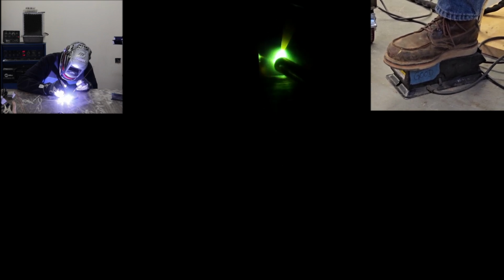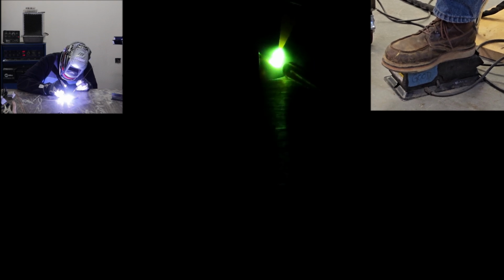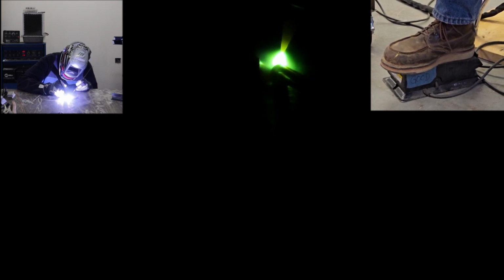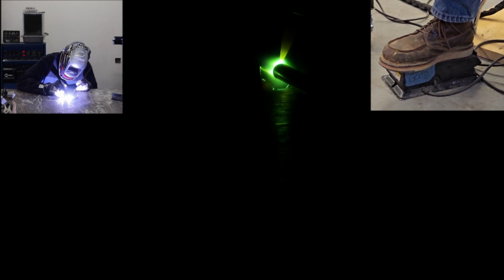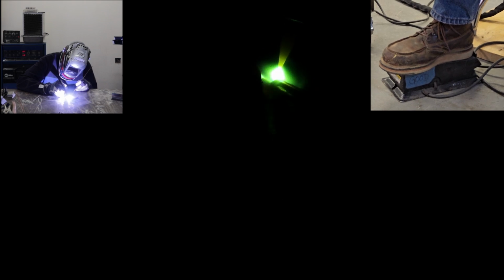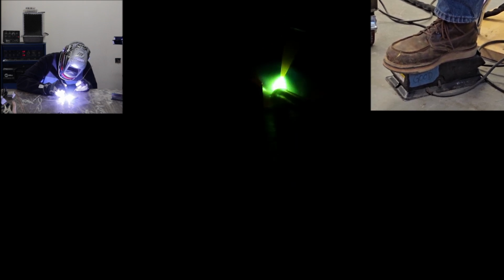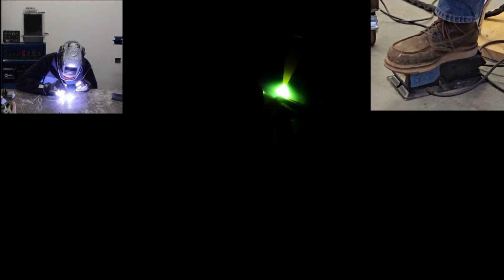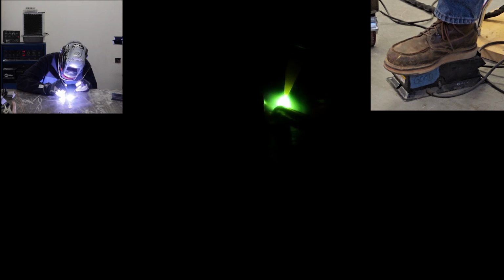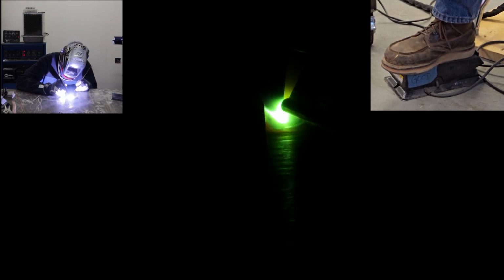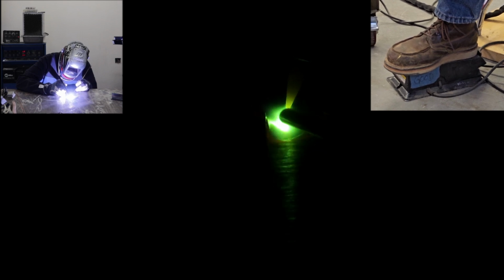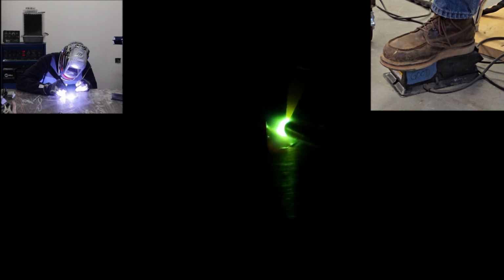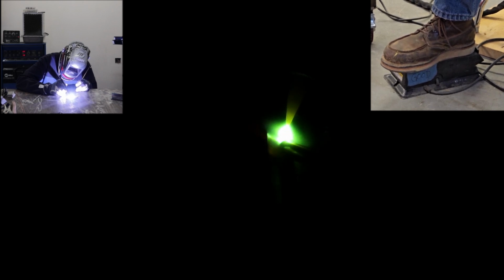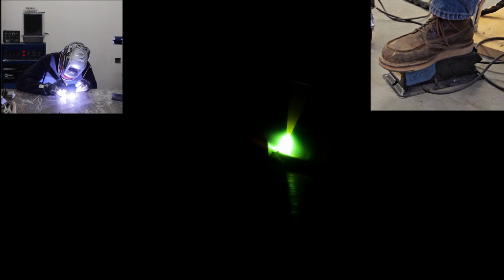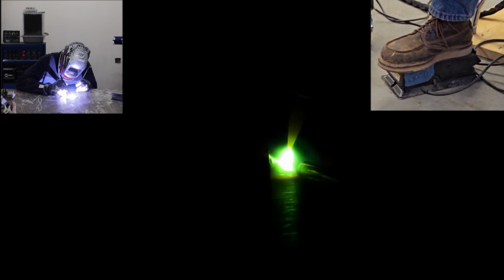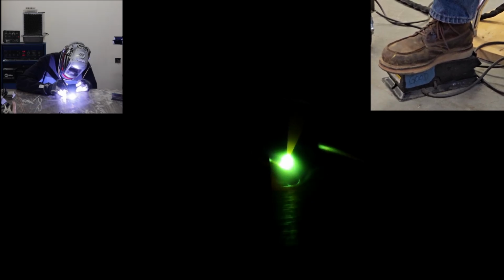Now my distance from the edge there is important because as I dip my filler metal in, I just want that top edge of my weld pool to lap over the top edge. We're using 10 gauge base material with a 3/32 filler metal. So that gives me a weld size that should lap over the top corner of that base material. So I'm just kind of watching the edge of my weld pool as I dip the filler metal in, and I should see it consistently consume that top edge to give me a nice rolled edge to my bead and just give me an overall pleasant appearance to the weld.